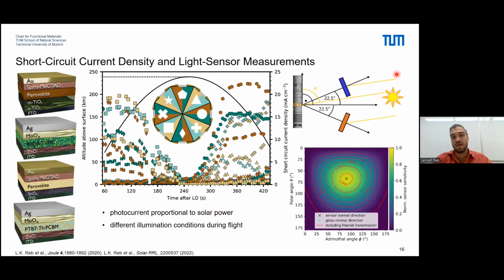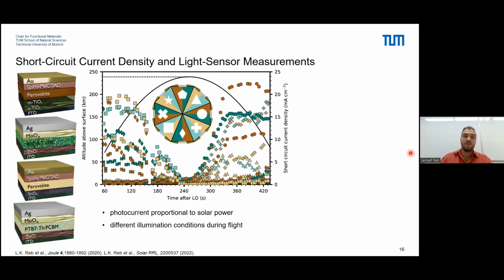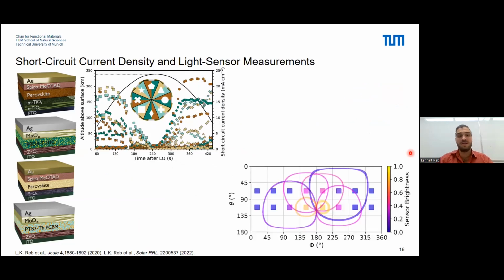We can also do a calculation, going to a sensitivity map of one sensor. This means if the sun is, for example, shining onto the sensor from this position, we expect a normalized sensitivity of 0.6. We can also turn this around. If the sensor measures 0.6, we know that the sun is somewhere on this contour plot of 0.6. By combining not only one, but all the 16 sensors that we have in total, we can draw multiple rings of the illuminated sensors. Exactly at the point where these rings intersect, we can allocate the position of the sun.